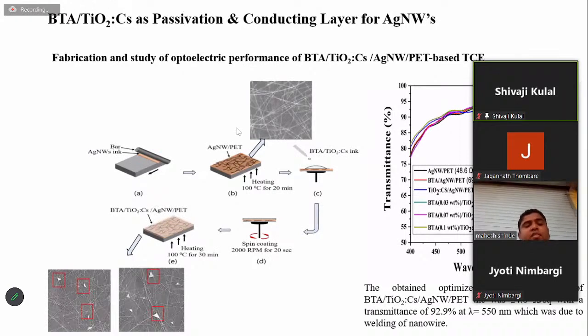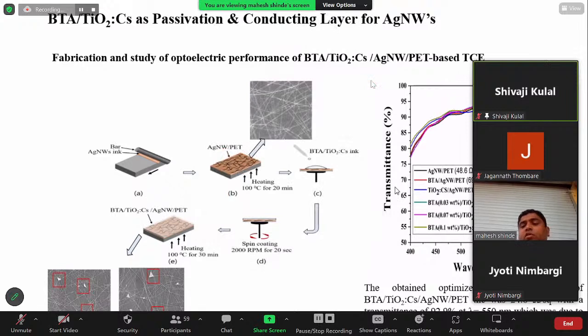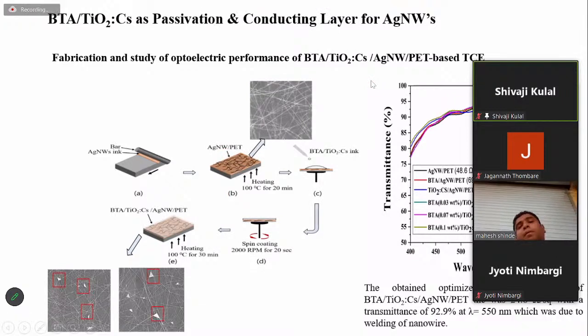After coating, we can see the welding of nanowires here, which is due to the BTA TiO2 solution, which generates heat through a chemical reaction, causing welding of the nanowires that we can see here. The sheet resistance for the silver nanowire PET is 48, but after coating the right amount, 0.03 BTA, the sheet resistance we get is relatively similar, 24, which is good enough for many devices. So we chose the BTA 0.03 weight percentage for our next experiment.